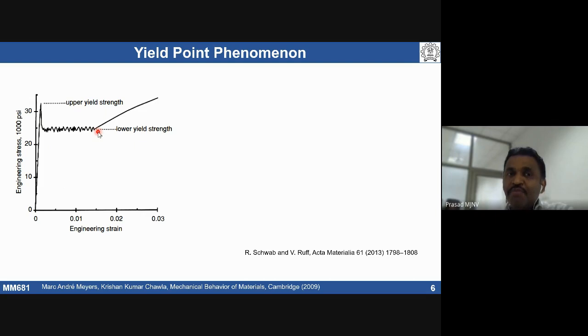After a certain dislocation density has developed, once more and more dislocations get built up, because we know that during deformation more and more dislocations can get generated and multiplied, then we are going to see the regular plastic deformation behavior of the material. During this yield point elongation, where we are talking about instability in deformation, it is one of the plastic deformation instabilities. This can lead to formation of some bands. Those bands are called Lüders bands.